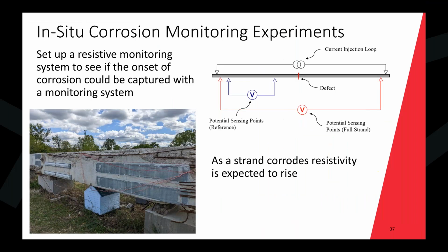And since we had connected everything for all of these monitoring systems for the cathodic protection and gone through that, we also thought we'd test whether we could actually make some in situ monitoring measurements using resistance on the prestressed strands to see if we could actually figure out when they were corroding and if they were going to break in that time period. So the idea here is very simple. We're measuring, relative to a reference, how much electrical resistance the strand has. The more corroded it is, the more we assume the resistance will go up.